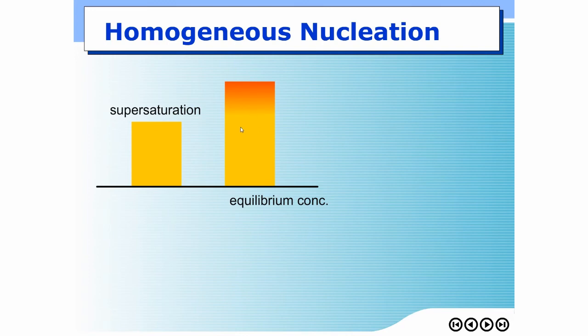Okay? We can do it by, let's say, producing more product if the growth species is formed by the reaction. If you increase the reaction rate to produce the products as much as we can, you can get high concentration of the product within a brief period of time, and supersaturation level will be high, like this picture. Okay, so we have an increase in supersaturation.